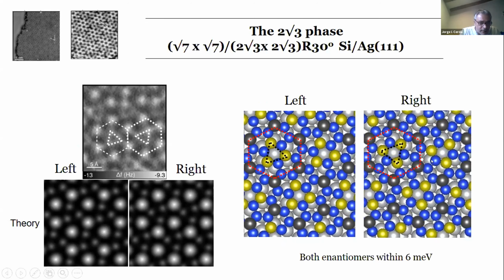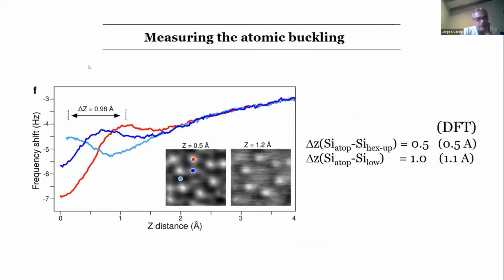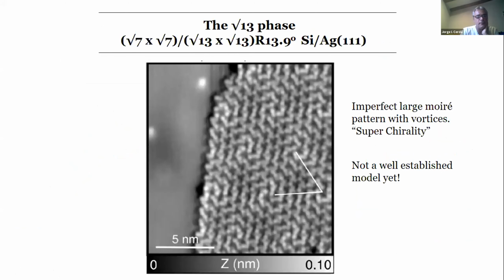Sorry, and yeah, as you can see here, these are the AFM images. You can see that we have this triangle pointing right, and here pointing left. So actually, this was the first time that we saw there was a kind of chiral nature of this structure. We again measured the direct mapping between the atoms, and here is the summary. We got 0.5 and 1, which are different types of silicon atoms, which correlates perfectly well with the DFT structure. So it seems that this approach of measuring directly the atoms keeps on working well.